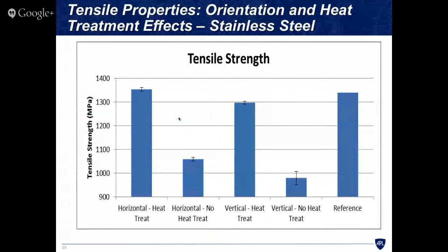People always ask, well, what about material properties? You've got your newfangled additive manufacturing, right? Well, how do the material properties compare to a casting or a forging? So here's some data that we took while I was at NIST. What we did is we built a series of tensile bars. This is a standard thing for engineers to do. And we built them horizontally along the build plate, and we also built them vertically. Of course you would expect intuitively that the bars that are built horizontally, that you pull this way, are going to be stronger than the ones that are built vertically. And that actually is the case.